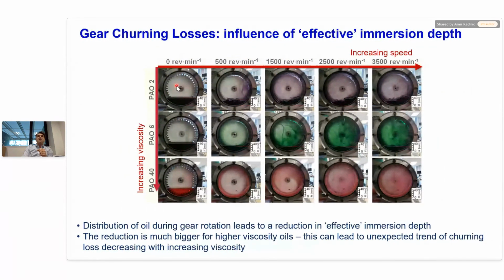And what you see is this focus on this immersion depth here. This is the oil. We started in each case with each oil with the same immersion depth. This is zero speed. As you run the gear higher and higher speed, the oil is being thrown up. Some of it comes back. So during the actual operation, there's a certain effective immersion depth. What that effective immersion depth is depends very much on the viscosity of the oil.